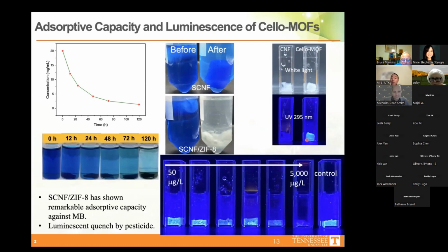Okay, so how can we manipulate this function? The MOF cellulose hybrid can show a luminescent picture right here, and we know that this hybrid can absorb chemicals. So then we applied it to absorb a pesticide called methyl parathion, which I think was banned, but has been historically widely used in the agriculture system. So we can use it to detect and sense the existence of this pesticide. For example, we made solutions of spiked pesticide from left to right, from low to high, and then we put these cellulose materials into the solution.